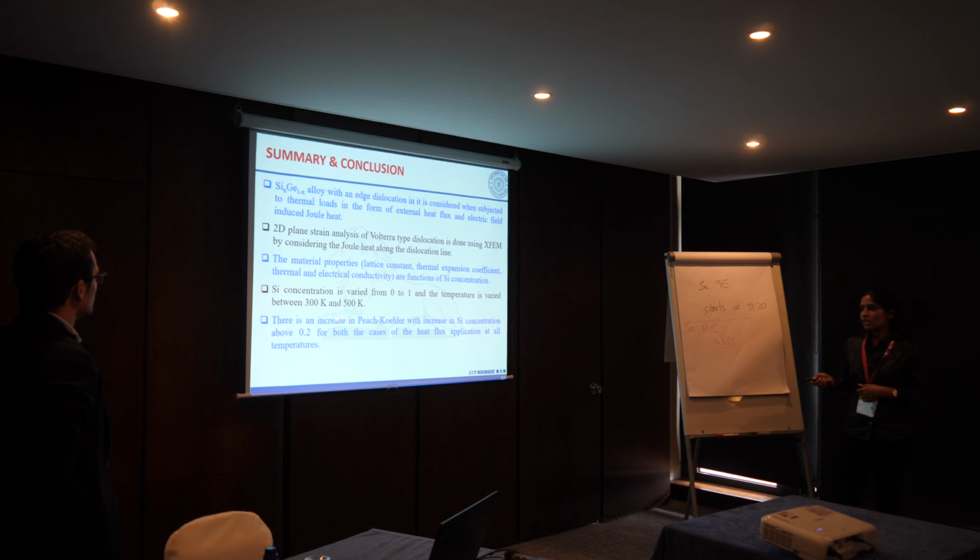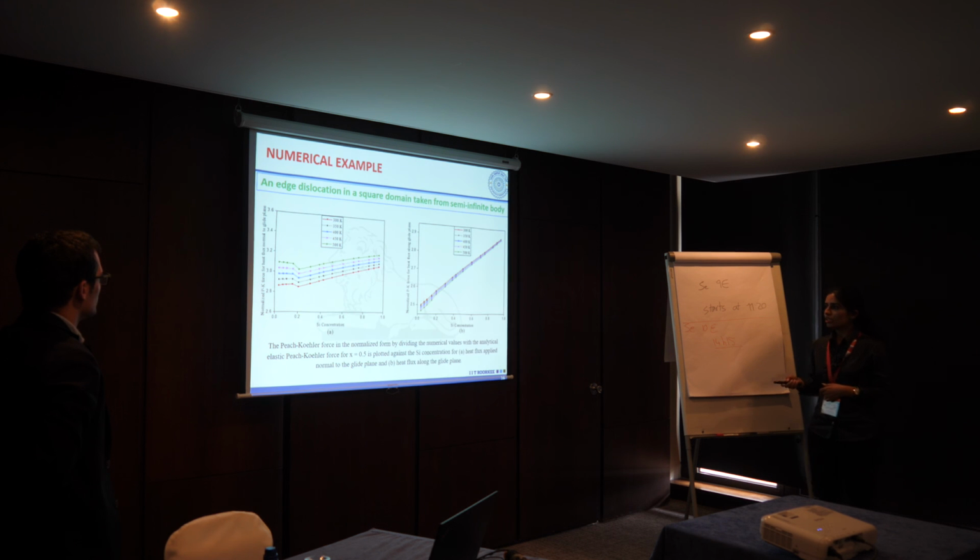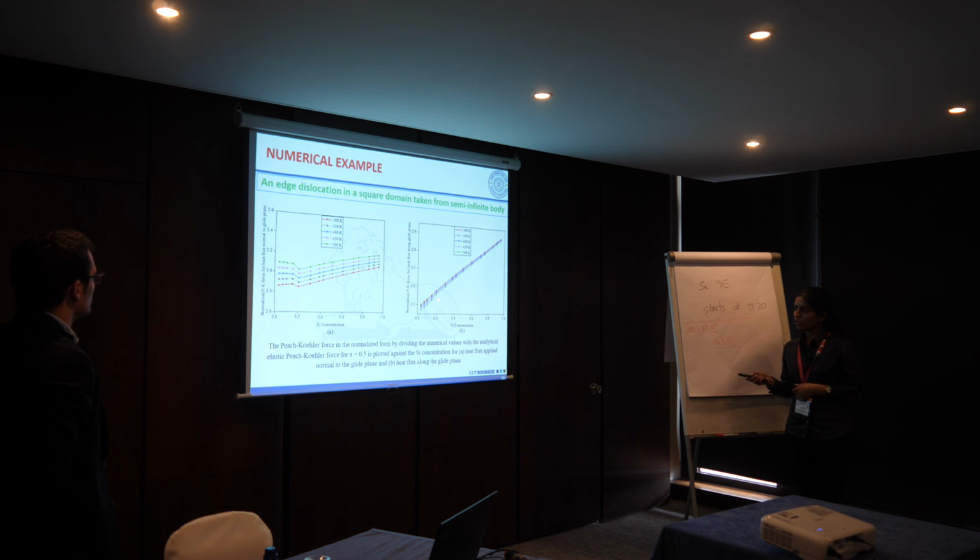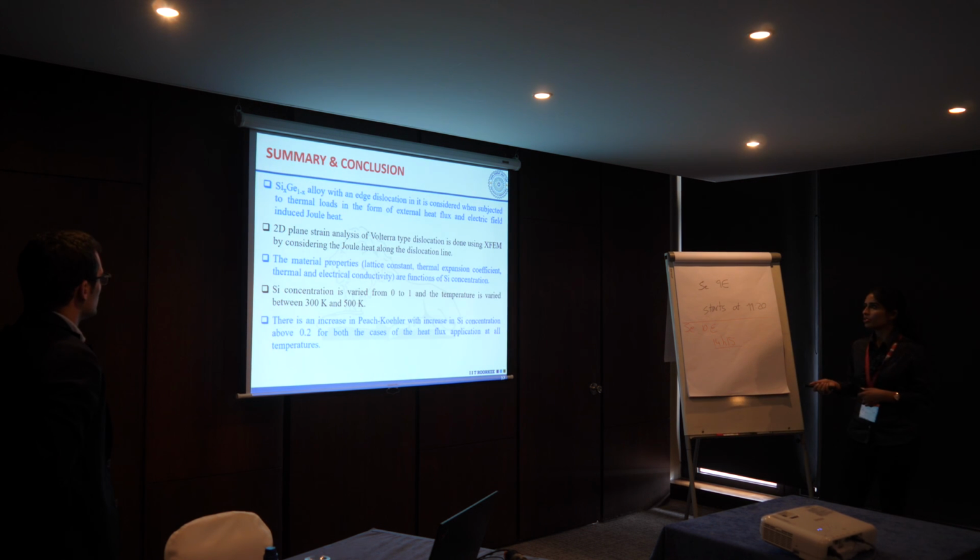We found an increase in Peach-Koehler force with an increase in silicon concentration above 0.2 for both cases. But below 0.2 there is a slightly different behavior for the two cases, that is, for the heat flux in different directions.